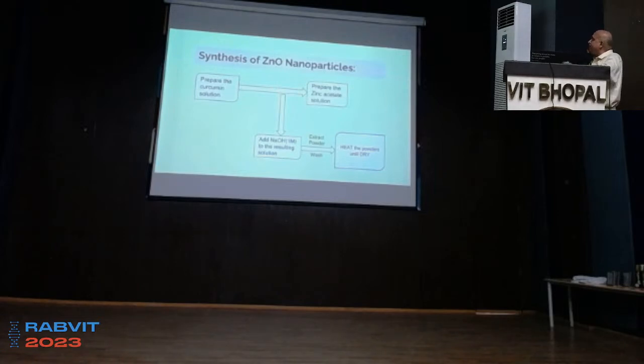Now, this is one example which we did here, your seniors did. This is one zinc oxide which was functionalized with curcumin. So, zinc oxide is known to be anti-cancerous, for drug delivery, antibacterial, and so is curcumin. So, we chose these two components. We found new materials, and what we found is we prepared the curcumin solution and the zinc acetate solution, mixed them, added NaOH. It seems very simple, but there are lots of steps in this process.